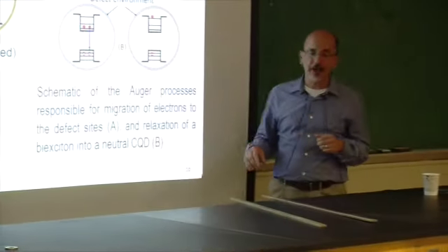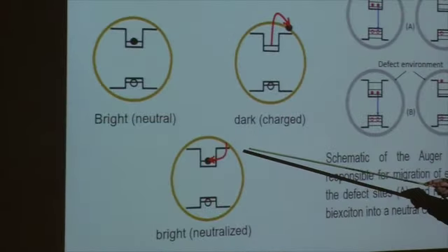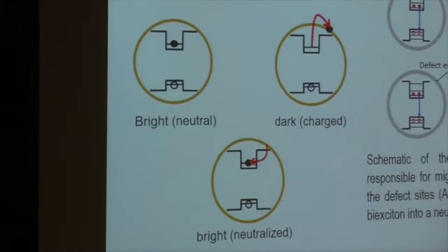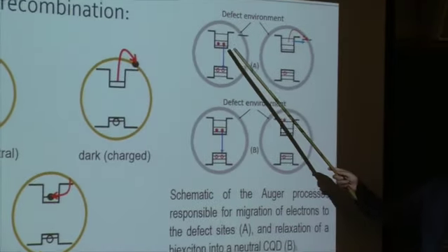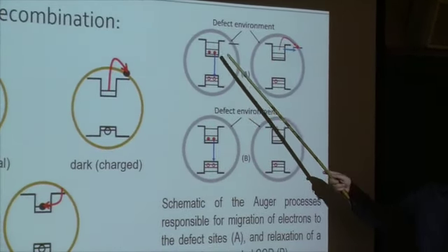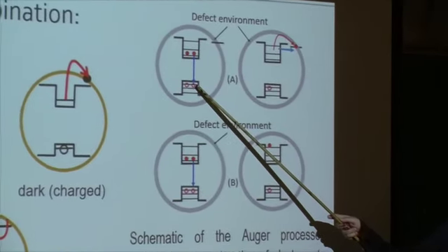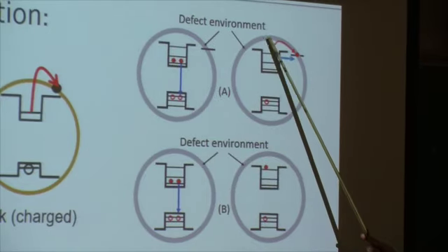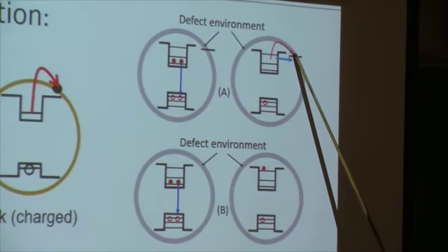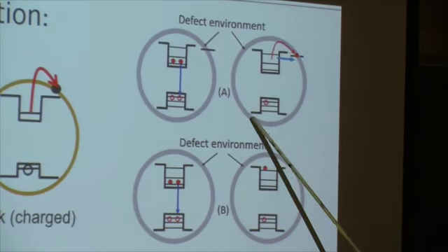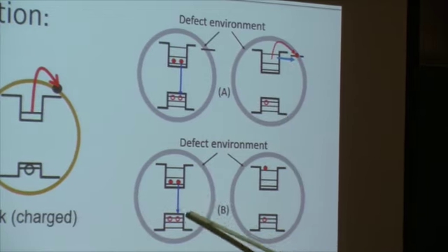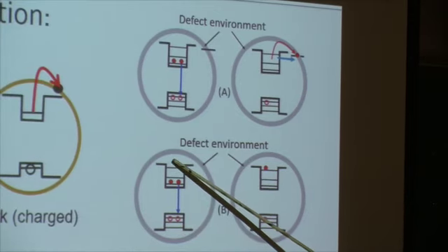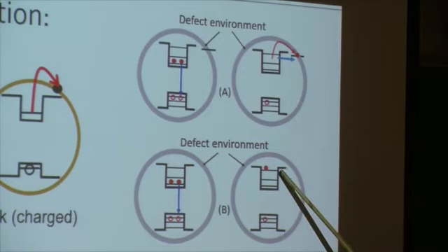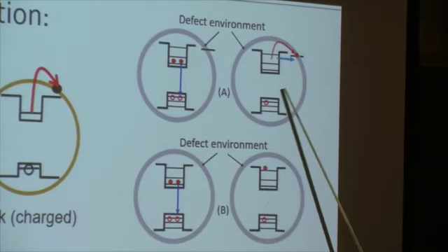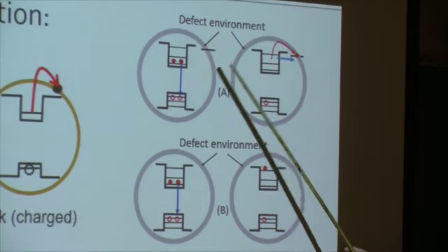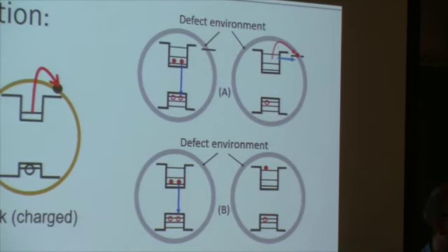And it is believed that the carrier comes back, and then the quantum dot becomes bright again. So these are two cases. You have two electrons and two holes. One recombines, but instead of giving you a photon, it takes that electron and puts it in the defect state, and this becomes dark. Or it gives off energy and just puts the carrier in an upper level, but this is not Auger recombination with a defect. There is Auger, but there is no defect. It is the defect that people believe is responsible for the blinking that you see.